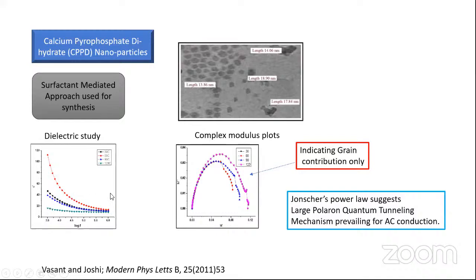The dielectric study shows a very interesting result: it is carried out at different temperatures, and as the frequency increases, the dielectric constant decreases. This is the typical behavior. Whenever an alternating electric field is applied, the dipoles try to orient themselves with the applied electric field. But when the frequency increases, the dipoles cannot comply with the orientation of the applied electric field, and that is why they lag behind. Ultimately, they show a steady state in nature. So at very high frequency, they don't show any other effect and become almost constant.